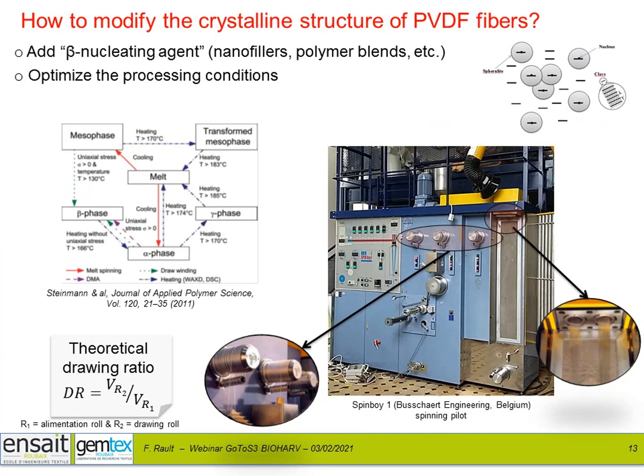There are several strategies for changing the crystal structure of PVDF. For example, nanofillers can be added to promote the formation of the beta phase. It is also possible to influence the crystalline phase conversion by adjusting the process parameters during the melt spinning. The drawing ratio is therefore an essential parameter to consider.